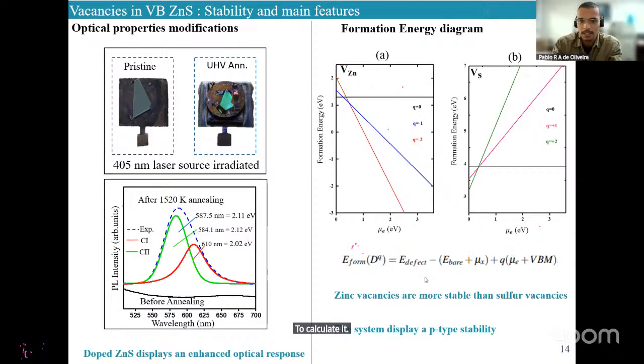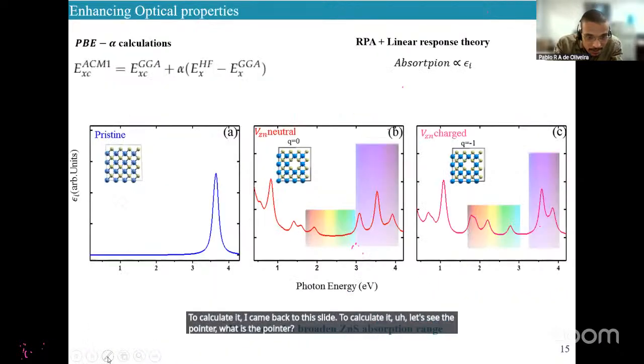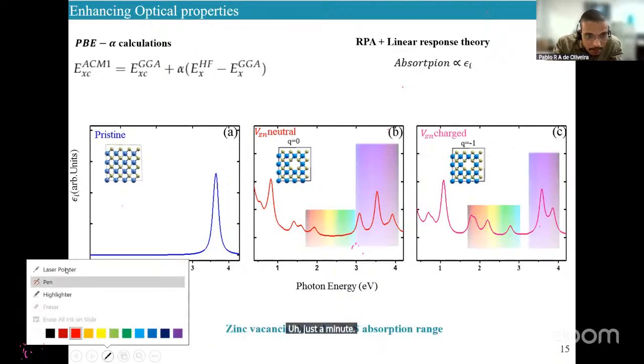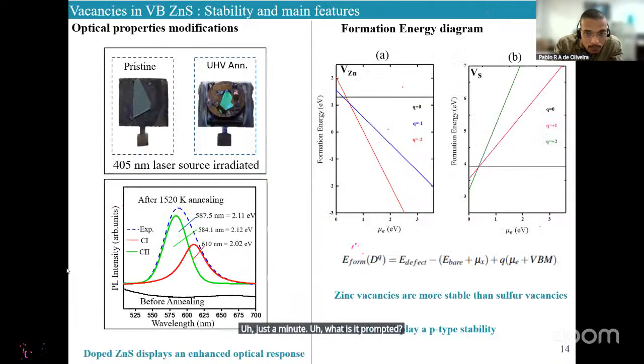I can go back to this slide. To calculate it, let's see the pointer. Where is the pointer? Just a minute. Where is the pointer? To calculate the chemical potential of zinc, you have to choose if you are dealing with a sulfur-rich or a zinc-rich scenario, you know. So basically, to compute this parameter, you have the total energy of the ZnS minus 0.5 of the total energy of the sulfur molecule S2 in the box.